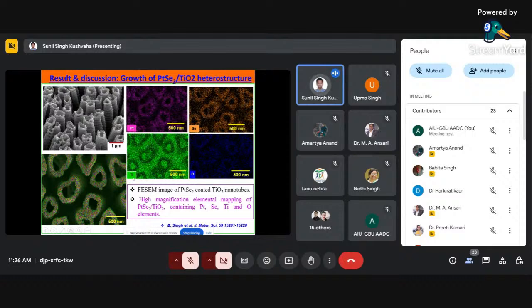Interestingly, when we are coming to this Ti or TiO2, here you can clearly see, of course, this material has been coated with the PtSe2, but also even below that one, because what of the space here or space is here, space is here. This is all also belong to titanium, because we use the titanium foil. So you can clearly see this titanium signal is larger compared to the platinum. So this is the one of the technique. Even people can see what kind of the elements present in the materials, and then accordingly you can see whether your required materials has been formed or not.